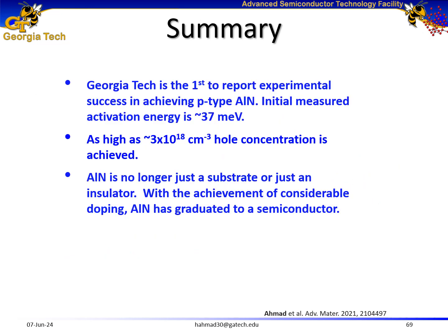To summarize the key results, we at Georgia Tech are the first experimental group to report success in achieving p-type aluminum nitride films with a very low activation energy of 37 milli-electron volts. We have achieved as high as 3 into 10 to the power of 18 per centimeter cube hole concentrations. And we believe that with this achievement, aluminum nitride is no longer just an insulator or substrate. It has graduated to a semiconductor.